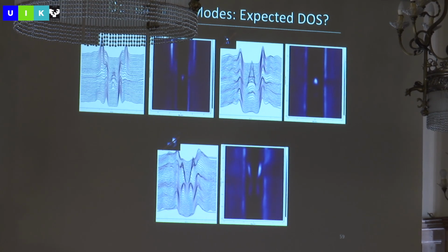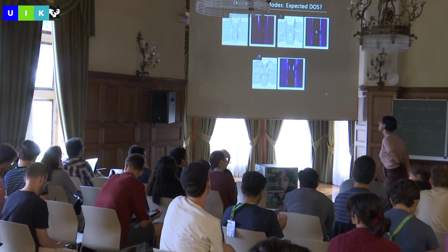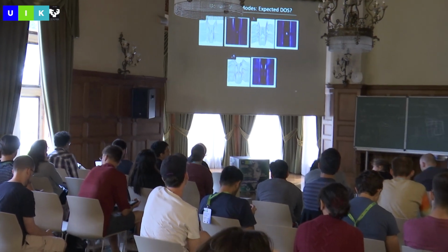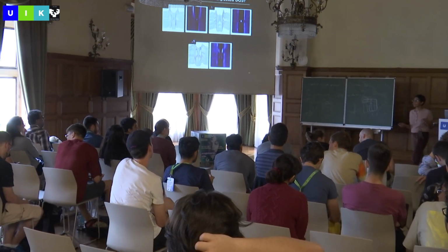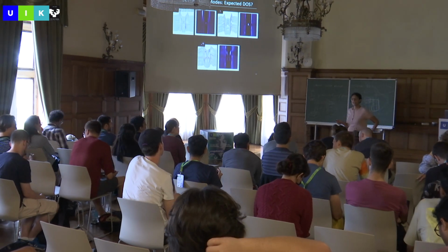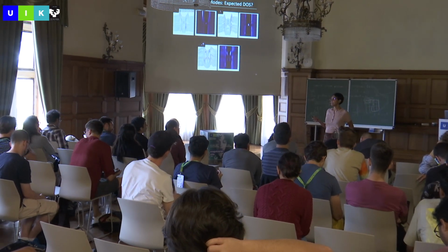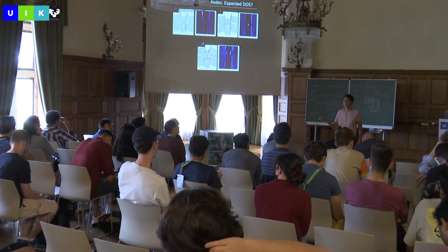Yes? It should. It doesn't. Oh, but it can. Where this scattering state is depends on the strength of the scatterer. So for a very, very strong scatterer, you end up getting a peak at zero bias. It's a Shiba state. Yeah. These are S-wave superconductors, and if you put magnetic impurities, you get Shiba states inside the gap. And so that's what they look like.